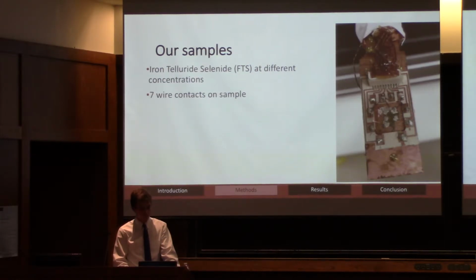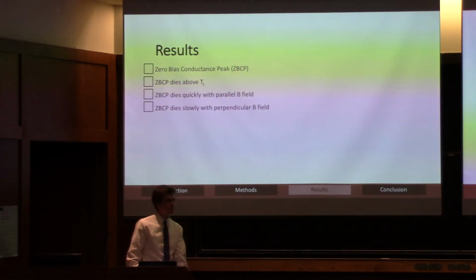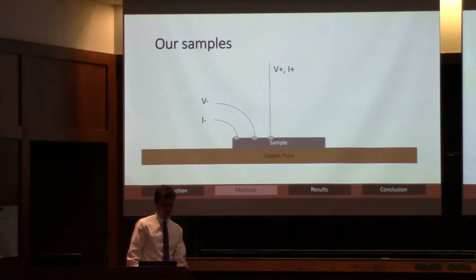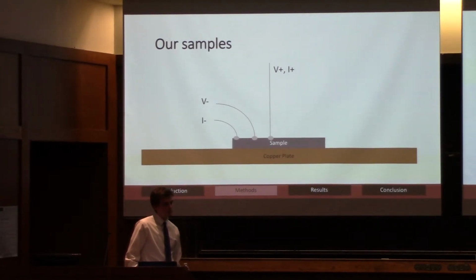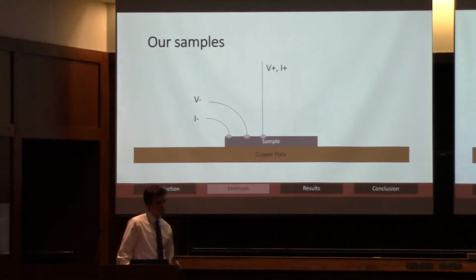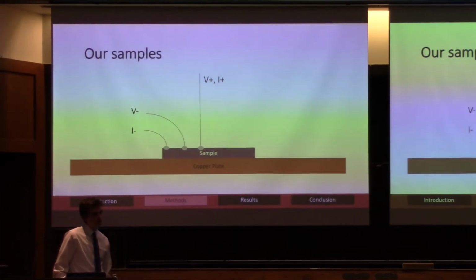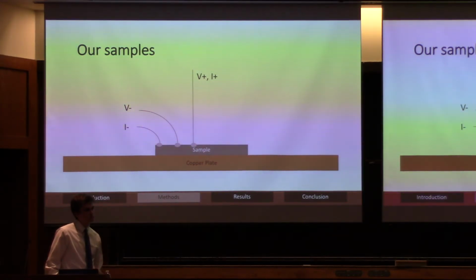Okay, so maybe the next slide, previous, where, yeah, so here, the V plus and I plus are the same wire? Yep, on the same wire, yeah. Okay. So we mentioned you use four-probe measurement, that if you take the I plus as a separate contact, then the V plus where you are taking the voltage signal won't have the effect of the homogeneous current that's initially sent in through the sample. You will get some kind of inhomogeneity when it's coming in at that spot. So I think that's the idea why people use the four-probe instead of calculating the current and voltage at the same spot. So I'm wondering, have you tried to separate your I plus contact?